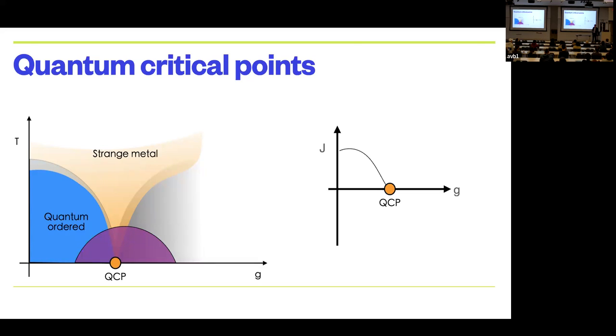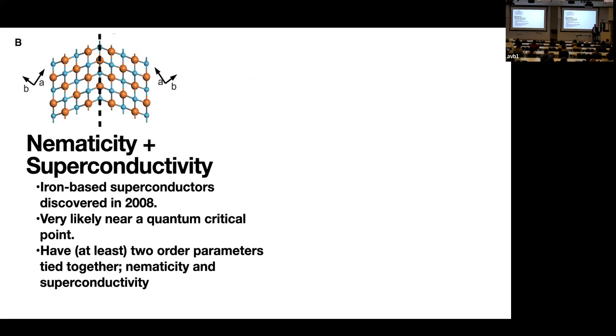It's embarrassing for all of us in Canada. But a lot of the unconventional superconductors that have the highest temperatures, highest TCs, often have their highest TCs around what appears to be a critical point, some vanishing energy scale in the system. This is controversial. Not everyone believes that this is what's going on, but I think phenomenologically, everyone agrees that this seems to be like a common feature in a lot of these systems. So one of the reasons why I'm interested in this problem is because studying these kinds of phase transitions that have this vanishing interaction scale, you tend to have new kinds of fluctuations and new kinds of physics that emerge that somehow lead to high temperature superconductivity. Okay, what's an example? I showed you before this orthorhombic crystal. This came up in a specific kind of material that I was studying when I was a postdoc called the iron-based superconductors that were discovered in 2008. And it turns out that these seem to be very likely near some kind of critical point, but the whole question for many years was what kind of critical point it was.